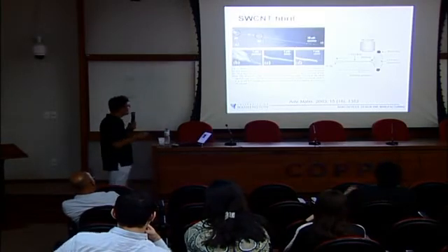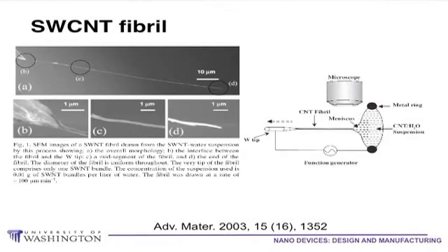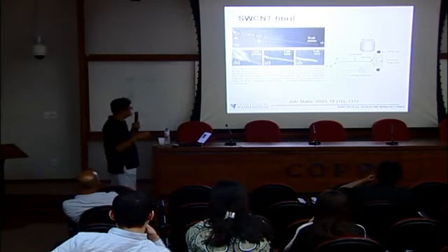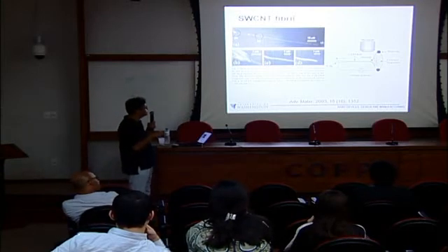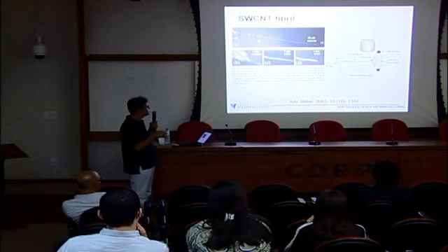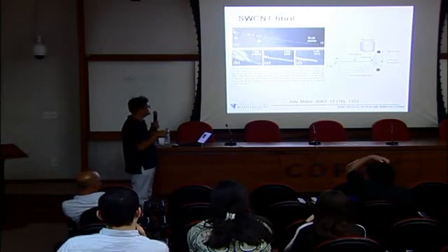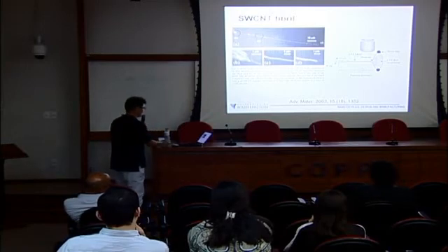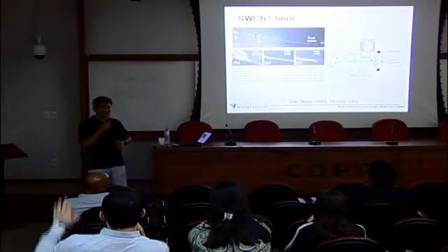And also we can make small fibers with capillary action and an electric field. In the solution, we have a bunch of nanotubes, and we use a sharp tungsten tip to attract the nanotubes. When we draw the tip out of this solution, we can form a fiber, which is this structure. Okay. So yeah, that's all the slides that I showed.